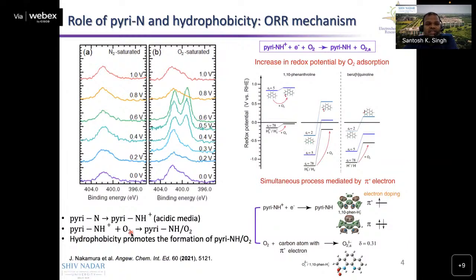For proving our concept, we took one bottom-up model catalyst, that was 1,10-phenanthroline, which has two pyridinic nitrogens, and we adsorbed it over the carbon surface, and that catalyst was utilized for the oxygen reduction reaction. Here we can see that in the presence of nitrogen, when we applied different reduction potentials, there was no change in the pyridinium ion peak. This pyridinium ion peak remains the same even after the application of potential in the presence of nitrogen. However, when we put in an oxygen saturated solution, we observed the generation of pyri-NH species. So that is the oxygen adsorbed pyri-NH.